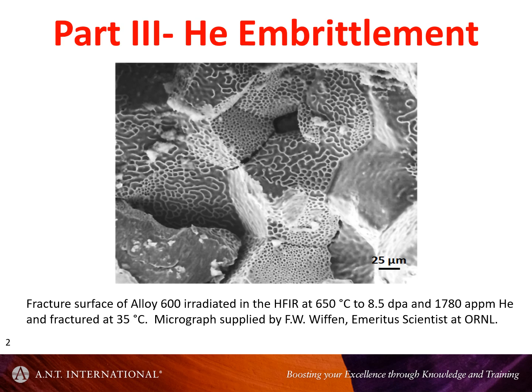Anyway, when this came up at the end of the 2000s, around 2009, an assessment document was written by our engineering group, and they talked about slip interactions with grain boundaries, and that's why we were getting the intergranular failure, with no evidence other than the fact that we were getting intergranular failure, and ignoring the fact that there were huge amounts of helium being generated. So, basically, two things then.